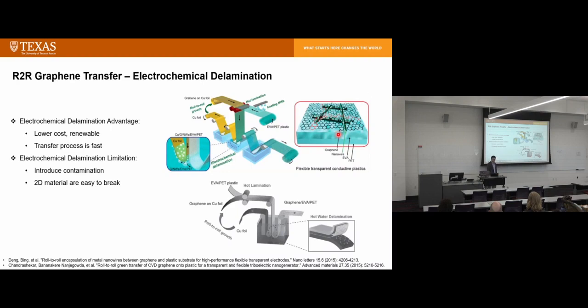Another method is called electrochemical delamination. In this process, you laminate your graphene with polymer, and then it goes through electrochemical baths. So you supply electricity to generate hydrogen bubbles inside this interface between your graphene, copper, and the top cover polymer. So this is the substrate you want to transfer the graphene to.